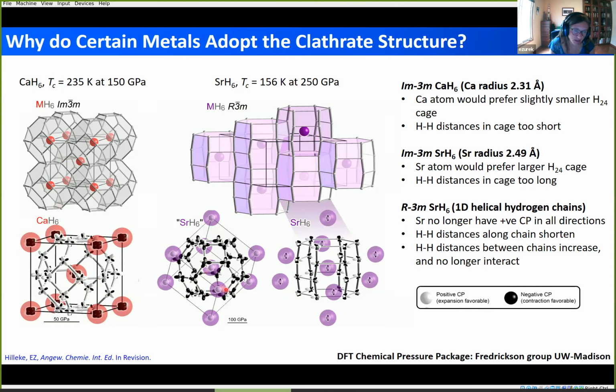That is what keeps this structure together. For strontium H6, on the other hand, we see white around the strontiums showing positive chemical pressure, so expansion would be favorable. However, within the hydrogen lattice, we see that it would like to contract—essentially the inverse scheme of the calcium H6 chemical pressure maps.